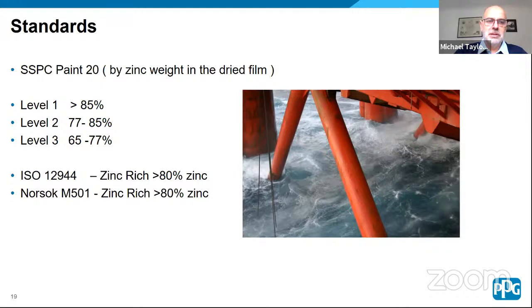There was a discussion of whether you need more than 85% to get good corrosion protection, but generally we find that coatings that contain even lower amounts of zinc than even level 3 can still give you very good corrosion protection, and in some ways better than non-zinc coatings.